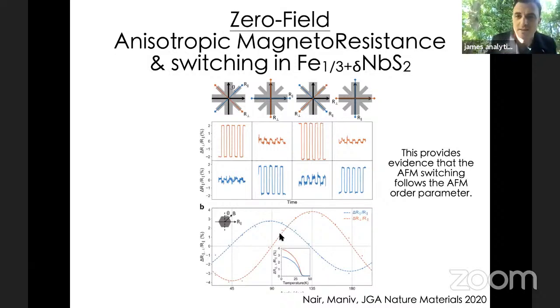But there's a few things that we don't understand. We don't understand this anomalous current dependence. We don't understand how the magnetic order connects to the rotation of the Néel vector. Particularly, you might remember, I purposely mentioned that the Néel order, the spin polarization, was actually mostly out of the plane, but the magnetic field and the current that we're applying is actually all in plane. So this wasn't completely obvious, and it still isn't completely obvious to us as to why it works, whereas all of the other antiferromagnets that we could switch all had in-plane magnetic order. Okay, so there's lots of things that we don't understand.